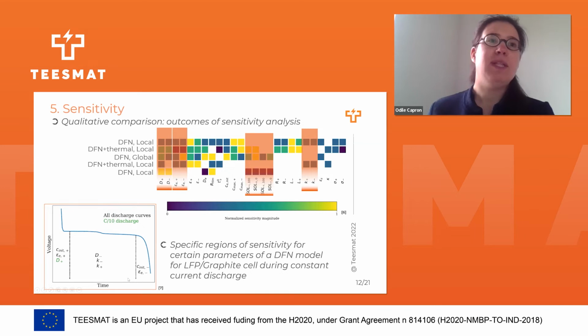Whereas in the middle range of the discharge, we can see that it's mainly parameters related to the negative electrode and related to the kinetics and the dynamics. So basically the diffusion coefficient of my negative electrode and the positive and negative reaction rate. So that kind of kinetics and dynamics related. And at the end of my discharge, the parameters that will influence would be the initial concentration of lithium or sodium ions in my negative electrode and the porosity degree of the negative electrode. So when we perform simulations and we want to compare with experimental results, it's good to have this in head.